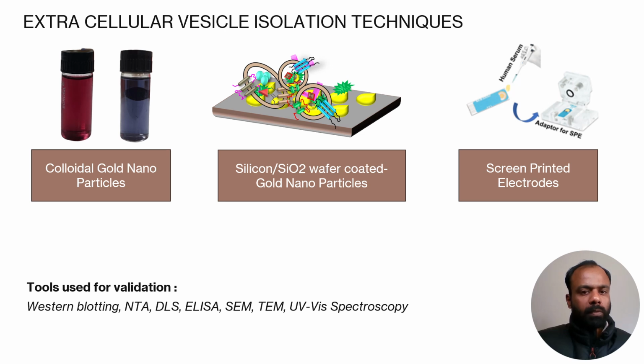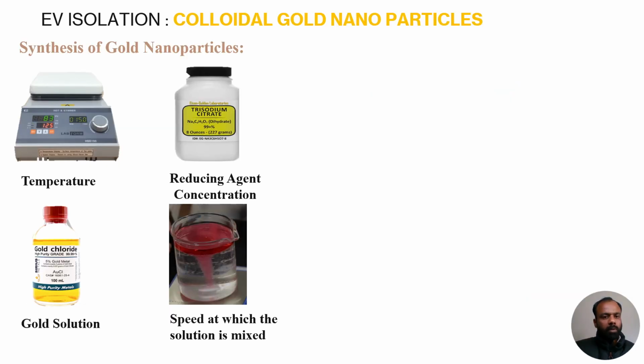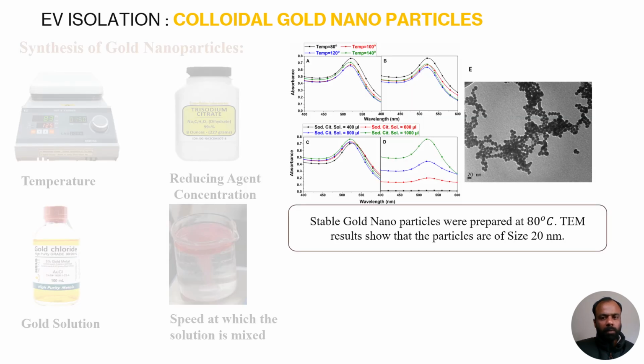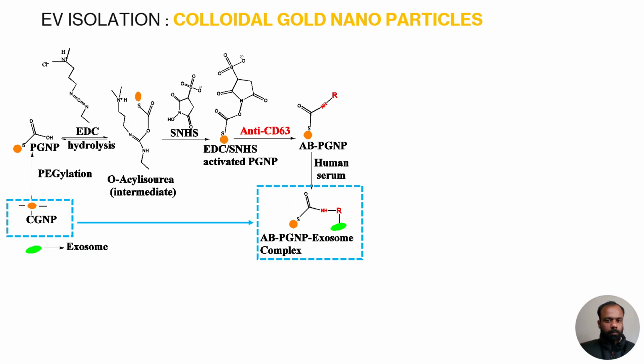Polyethylene glycol, EDC-NHS coupling chemistry were used to isolate extracellular vesicles in various means, that is by using colloidal gold nanoparticles, silicon wafer coated with gold nanoparticles, screen printed electrode with gold working electrode. To synthesize gold nanoparticles, various input parameters were optimized and tested in UV visual absorbance spectrophotometer. The TEM results show that approximately 20 nanometer sized gold nanoparticles were synthesized.